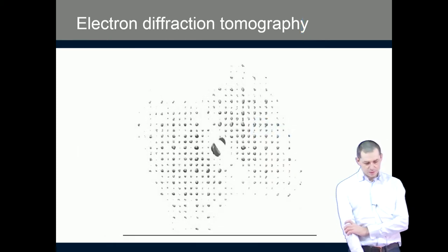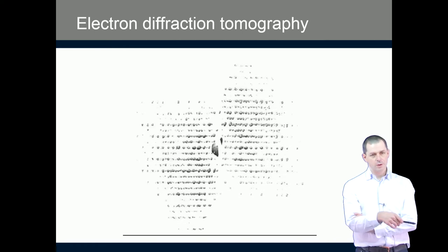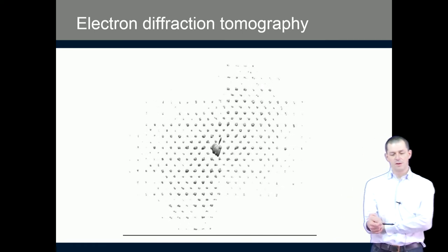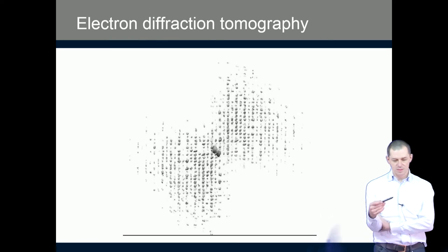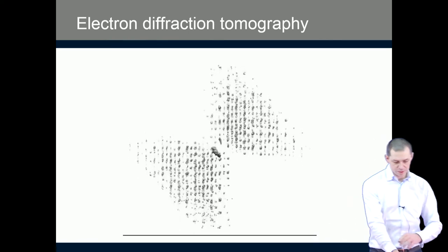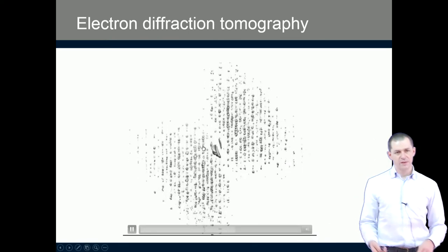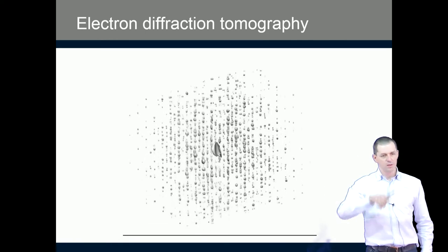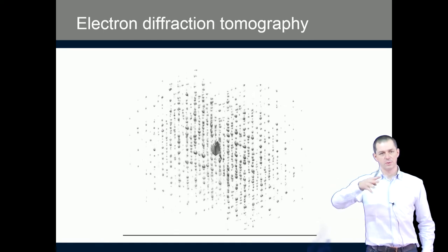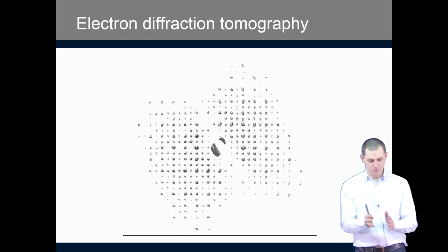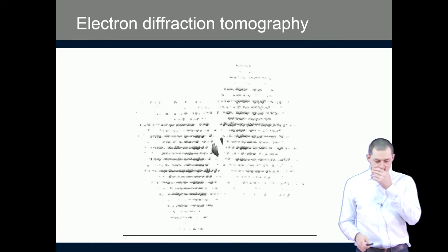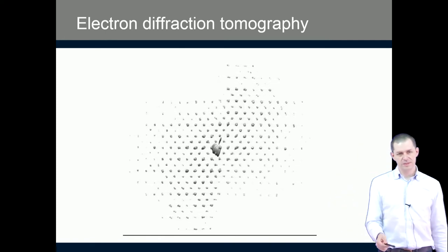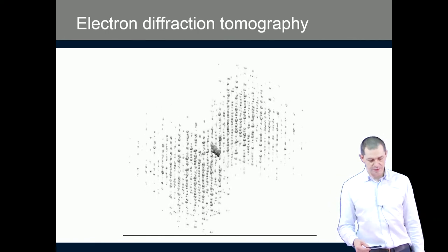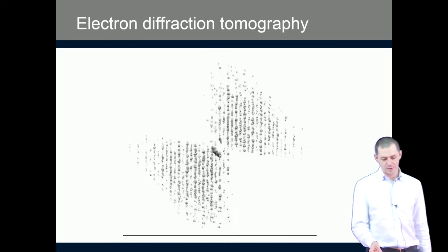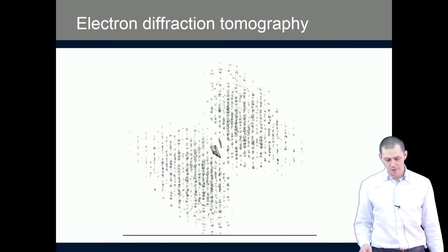This is then the result of such data collection. It's a three-dimensional rendering of reciprocal space. So we have good coverage. You see this missing wedge here. This is because in the electron microscope we cannot rotate the crystal all the way around. There is always a certain limit on the tilt, so we have a missing wedge of data. But apart from that missing wedge, the coverage of reciprocal space is complete, and we can extract intensities of all of these spots.